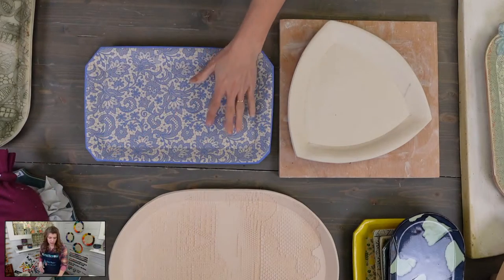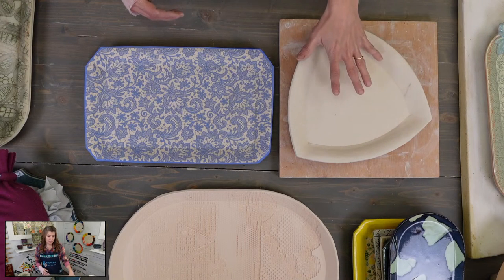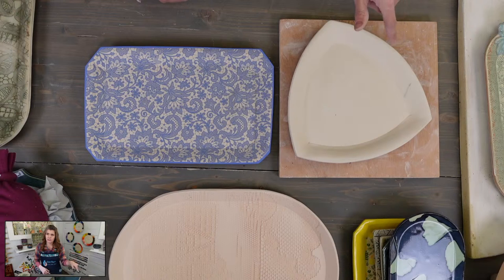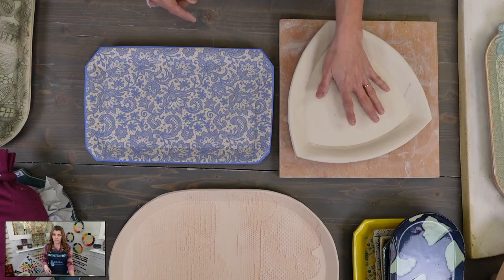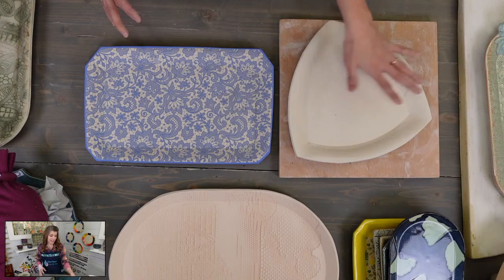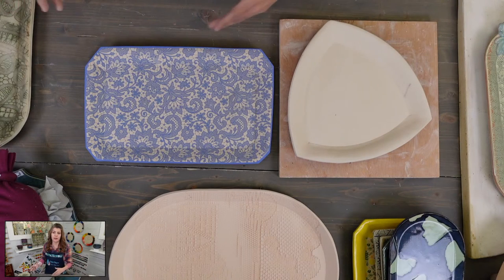Say I was going to carve a plate that was just made. It comes off the form — it's probably still a little too wet. So I will cover it again with plastic, weigh it down, and the next day come back to it, wax it. If I'm going to mishima it, let the wax dry all the way, cover it with plastic and weigh it down another day, then come back on day four after making. Making day, moving off the form and drying day, waxing day, carving day — four days. Same thing if putting slip underglaze for sgraffito. Let it air dry enough, put the plastic back on, weigh it down again, and leave it weighed down. After carving, go back and weigh it until completely dry. The weighing happens as long as I'm not working on it.